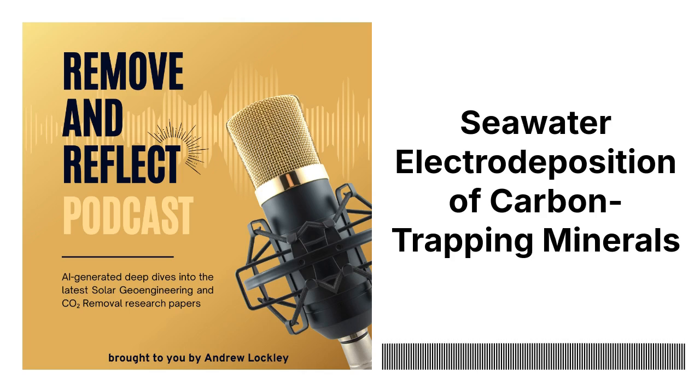Right. And they observed something interesting about the current density. Yeah, they found that as the process went on, the current density tended to decrease. And why is that important? Well, surprisingly, it seemed to help the minerals adhere to the electrode and grow without detaching. It's like the lower current density created a more stable environment for those minerals to grow. So they could control the size of the aggregates. Yes. What about the shape? They found that they could actually influence the overall shape of those mineral aggregates by using cathodes with different shapes. So the shape of the electrode actually dictated the shape of the mineral deposit. Exactly. And it opens up all sorts of possibilities for designing these materials, like creating aggregates with specific shapes for different applications.